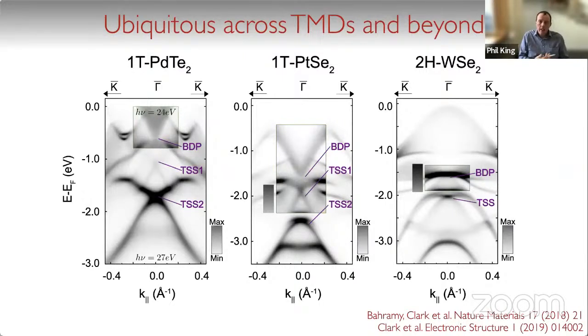In fact, we think this basically occurs across the whole of the transition metal dichalcogenide family, where you naturally get this disparate out-of-plane dispersion of the pz versus the px and py states. Just as a brief example, these are the measurements that we've been looking at in palladium ditelluride. But you see very similar things in the sister compound platinum selenide, where we have a bulk Dirac cone and a pair of topological surface states arising in this material.